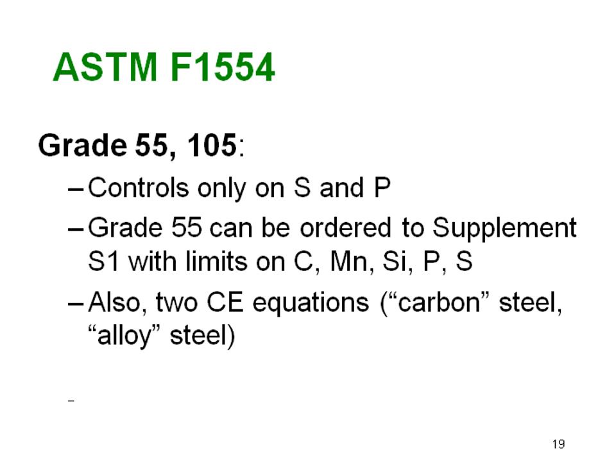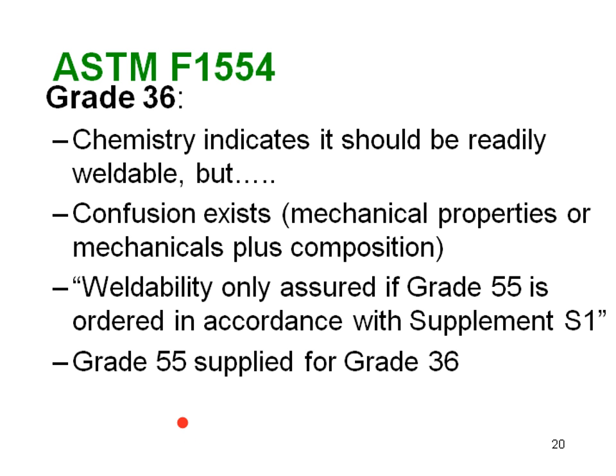Well, let's continue and examine then grade 36 from a welding point of view. Now, the chemistry would imply it should be readily weldable, but there is confusion as to whether or not appropriately grade 55 can be substituted for 36. 36 has some chemistry controls that 55 doesn't necessarily meet. And the specification for 55 specifically says, quote, "weldability is only assured if grade 55 is ordered in accordance with supplement S1." So we have grade 55 that might be substituted for 36, but 55 has weldability assured only when I order it to S1.